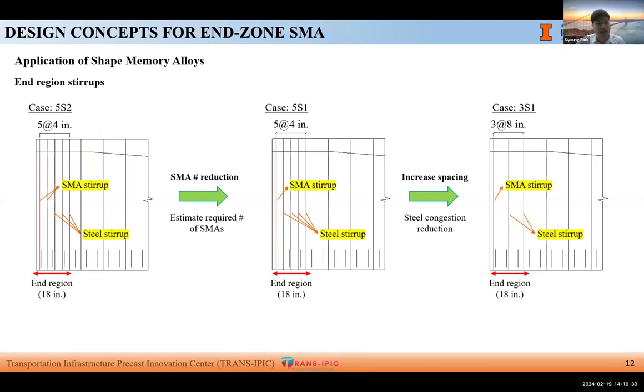To graphically see this, in case of 5S2, 2 SMA stirrups were replaced to mitigate the crack damage shown in BT72 case. After that, the number of SMA stirrup was reduced to 1 to also see the effect with a smaller number of SMA. Actually, it would be best if we can replace small number of SMA with sufficiently relieving damage. After that, the number of end region stirrups was reduced to 3 with 1 SMA stirrup. This was to reduce steel content while limiting crack propagation. In total, original steel case to 3 SMA cases were compared in terms of cracked area, cracked width, principal strain, and stress distribution in end stirrups.